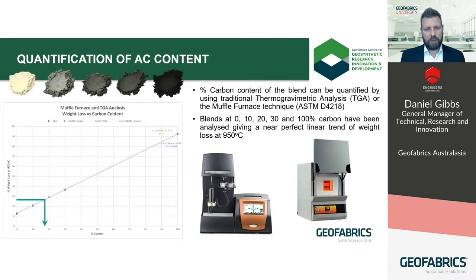So we realized it was important to add a quantitative test for when it arrives on site to determine the amount of activated carbon inside the blended powder for CQA purposes. And that's where the percent carbon content test comes in. You can use either thermogravimetric analysis, or TGA, to quantify this, or you can use the quicker and cheaper, but by no means less precise, muffle furnace test.